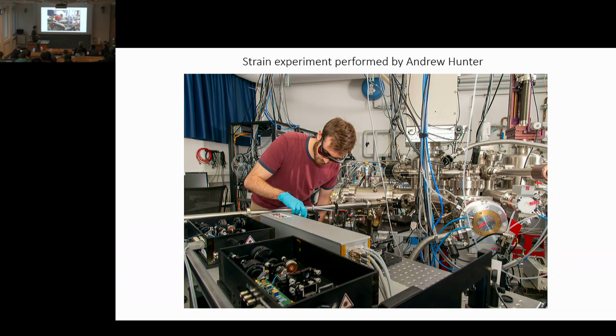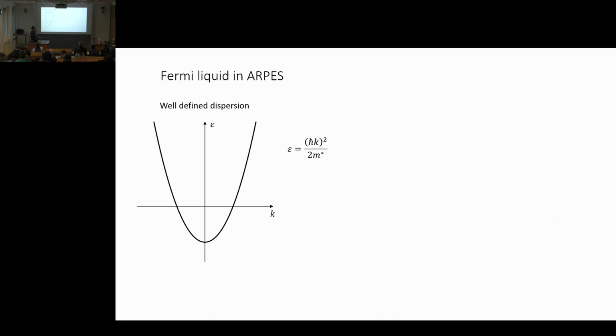The experiment I'm going to show you was actually not performed by me, but by Andrew Hunter, right in the lab across the hall, about 50 meters in this direction. And to give you an idea of what to look out for, as you've seen, we see the dispersion of the quasi-particles with ARPES. In particular, we see the mass of our quasi-particles with varying degrees of this curvature. In principle, this mass can also be negative, so we have a hole-like band.